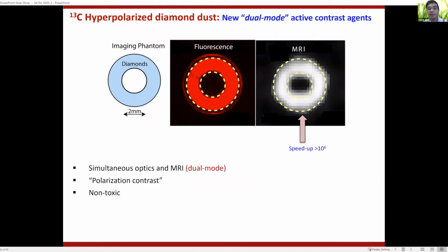You can also use the simple fact that optical imaging has very high spatial resolution. You can really get down to the diffraction limit, which is less than a micron. But optics suffers from optical scattering. If you try to image particles in tissue or in milk, or any sort of real world medium, the resolution blows up exponentially, so you get very poor resolution. But MRI is RF imaging, and MRI does not suffer from scattering. So there's a chance to combine the good features of optics, which is high signal to noise, with MRI, which is scattering free, apart from the fact that you can get this Fourier conjugacy.